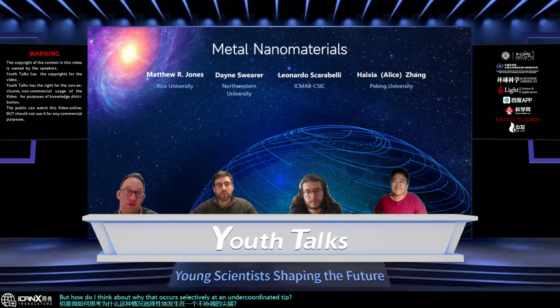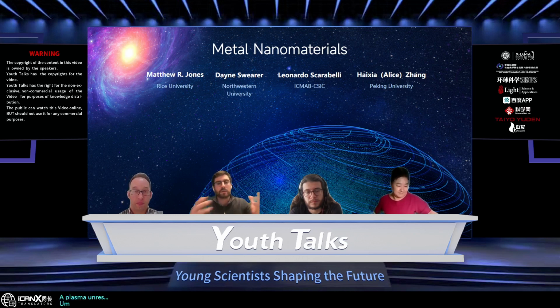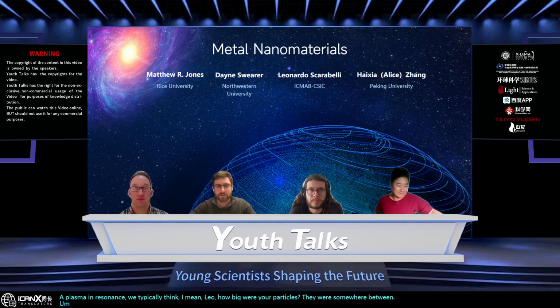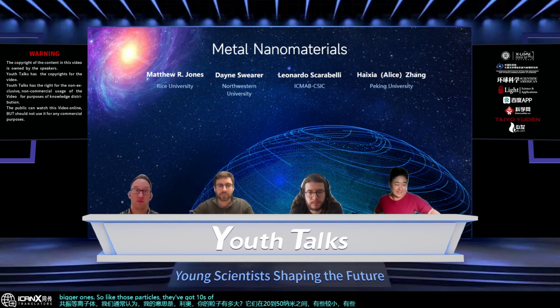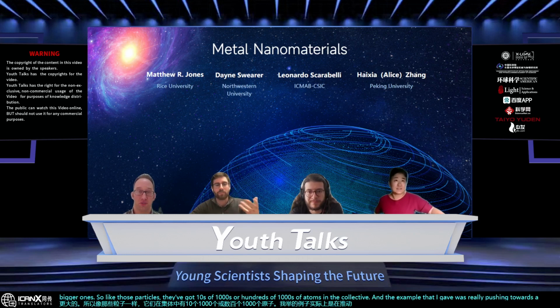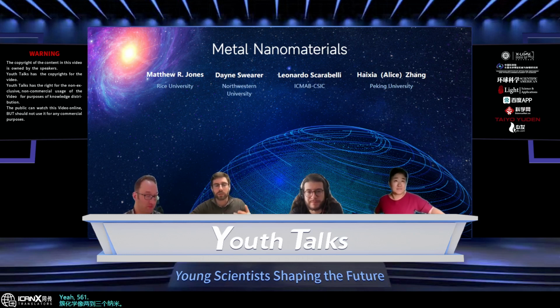Right. Yeah, that's a really great question. To put everything into context, in terms of a plasmon resonance, we typically think, I mean, Leo, how big were your particles? They were somewhere between like 20 and 50 nanometers or so, some smaller ones, some bigger ones. So those particles have tens of thousands or hundreds of thousands of atoms in the collective. And the example that I gave was really pushing towards cluster chemistry, like 2 to 3 nanometers. Yeah, 561 atoms. And so it's really this atomistic simulation, and I think it's just that limit.